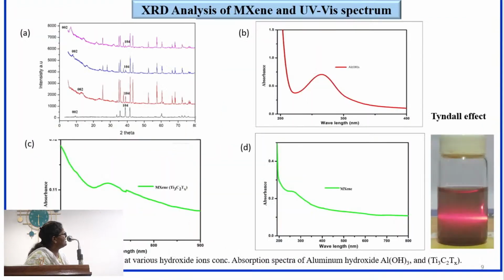This is the X-ray analysis of MXene. While increasing the concentration of hydroxide, MXene forms and the 104 plane, which indicates aluminum, is reduced. The UV-visible spectra indicate that the etched aluminum forms aluminum hydroxide, and also confirm the formation of MXene. Only the phase-pure Ti3C2Tx MXene appeared, and it shows the Tyndall effect with highly dispersible ability due to OH and Cl terminal groups.